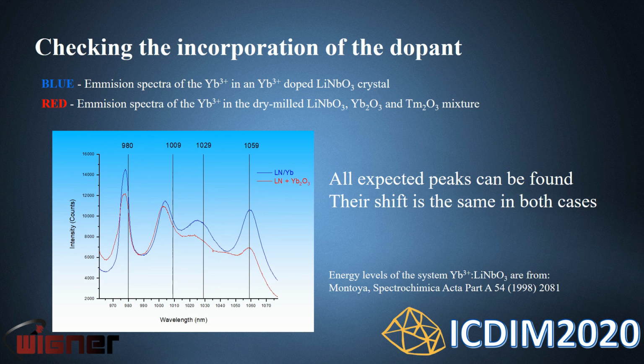For checking the incorporation of the dopant, photoluminescence technique was used, where the emission of ytterbium in lithium niobate could be recorded. Because all expected peaks can be found in the spectra and their shift is the same in both cases, we can say that they are in the same position. So the ytterbium ion is built in the lithium niobate phase in the second case as well. So sample preparation from raw materials can be used also.